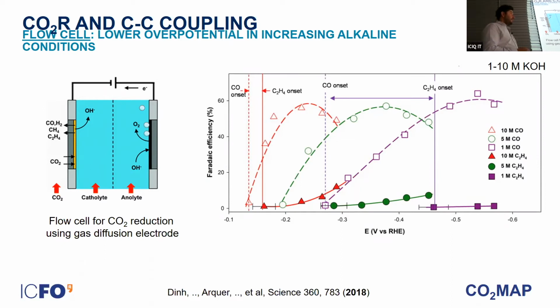Well, we learned that if you move to very alkaline conditions, you can reduce the overpotential a lot. That means the volts that you need in order to produce ethylene. You could see here these violet lines, the Faradaic efficiency for CO and for ethylene.